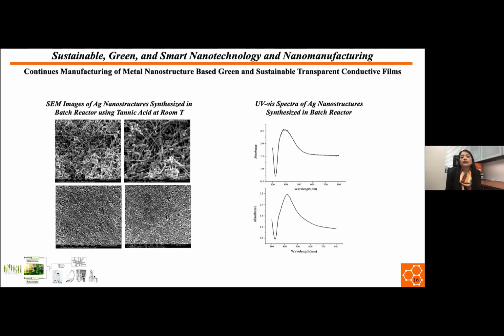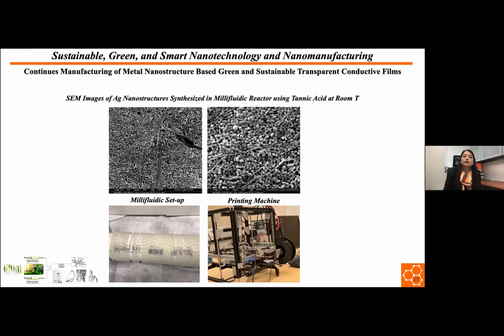And here are the results from the batch synthesis of silver nanostructures. However, as I mentioned, we are interested in continuous synthesis of these green metal nanostructures, these one-dimensional silver nanostructures. We have recently used a new setup for the millifluidic synthesis of silver nanowires, or silver nanostructures in general, because we still get lots of other nanostructures, including nanoparticles, in this system to continuously produce silver nanowires. The yield of silver nanowires, or one-dimensional silver nanostructures, in this system is lower compared to the batch one that I showed you in the previous slide. However, we believe that by modifying the millifluidic setup and controlling some reaction parameters as well as reactor design, we will be able to increase the yield of one-dimensional silver nanostructures.